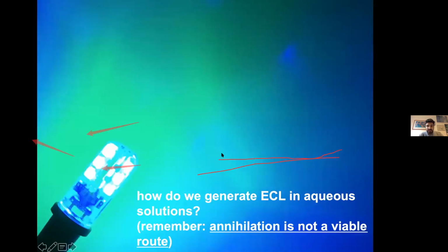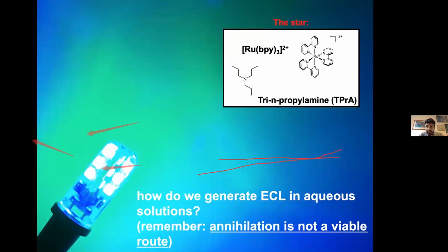So how can we generate the light? How can we generate light in aqueous solution and without annihilation, because the potential window in water is too small for the annihilation method that I showed before? We can generate light with these two species. Basically, ruthenium tris(bipyridine) is the main ECL dye, and it was developed for the first time by Bard and coworkers.